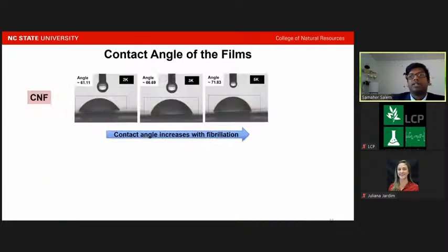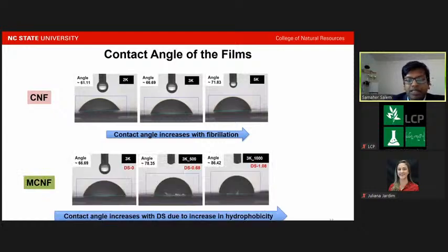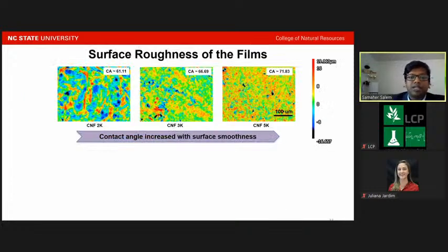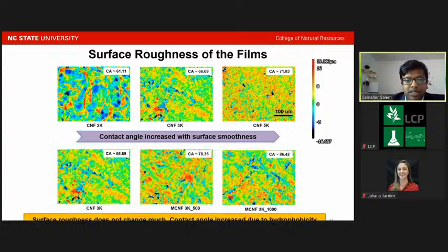We also measured the contact angle of the films, and we could see that the contact angle increases with the fibrillation. We also found that the contact angle increases with the degree of substitution due to the increase of hydrophobicity. We also measured the surface roughness of the films, and we could see that the surface roughness decreased with the fibrillation, and thus it affected the contact angle, which increased with the surface smoothness. The higher surface smoothness resulted in a higher contact angle and thus better barrier properties. The surface roughness does not change much with the modification. However, due to the presence of the acetyl group, the contact angle increased. This also explains why, due to modification, the contact angle increased for the nanofibril surface.